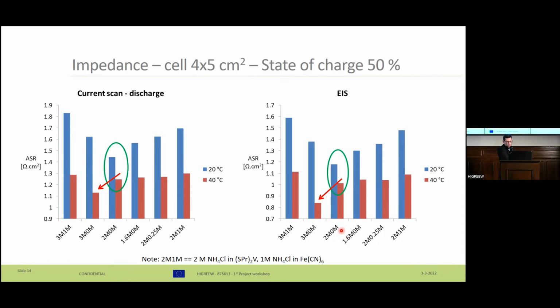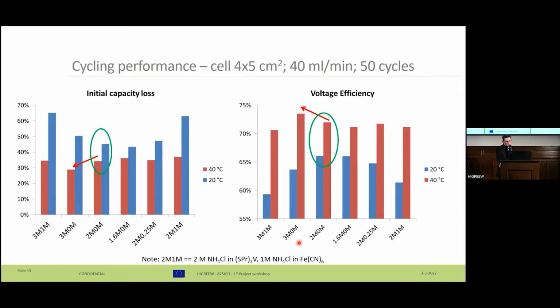But if we cycle the battery at the higher temperature, the best combination of supporting electrolyte concentrations is 3M0M. This data corresponds to some cycling performance like voltage efficiency and initial capacity loss. It means that the system with lowest resistance has the best voltage efficiency at given temperature. But if we go higher with temperature, the system 3M0M wins, as I mentioned earlier.